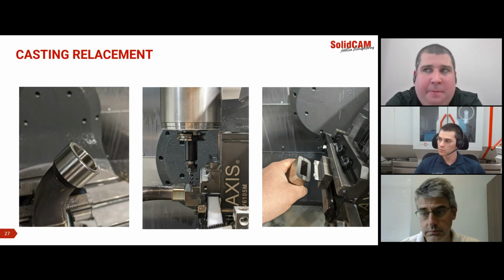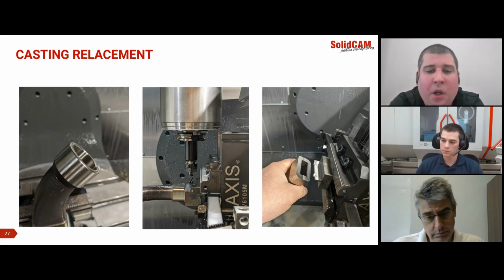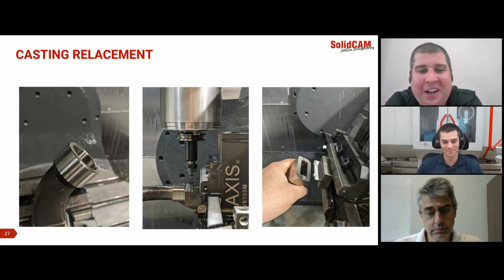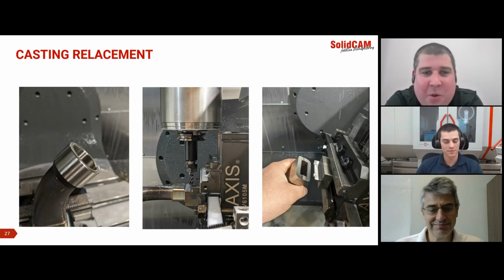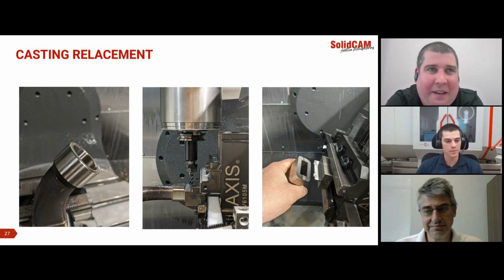In terms of machining, when we're doing machining work with flood coolant or through spindle coolant, obviously there's going to be quite a bit of coolant mist in the machine. The Meltio head retracts up into a deployment mechanism, which has trap doors that protect the Meltio head from coolant and chips while we're machining. We also lock out the coolant pump while we're doing additive work. That way there's no way to accidentally have an end user turn the coolant system on while you're printing. My kind of joke is that it would be an expensive accident if you were turning the coolant on while you're laser welding, but that's prevented with some macros that we have in the background.